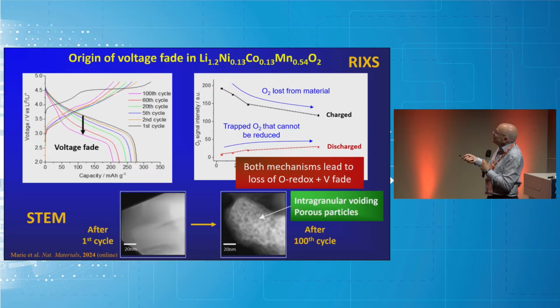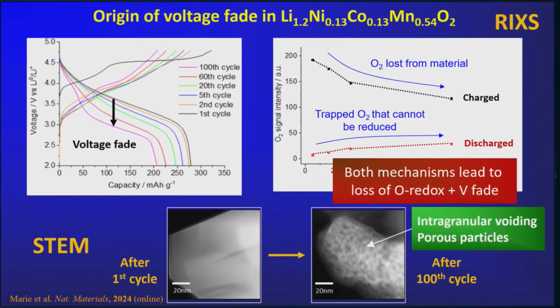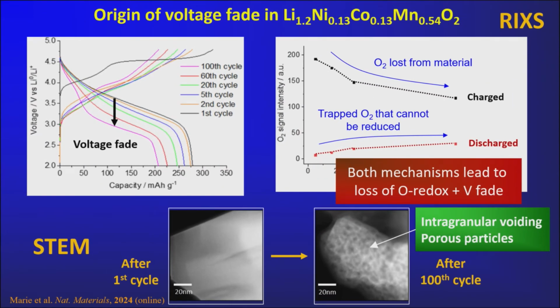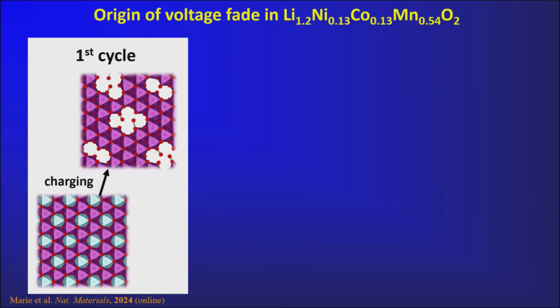And if you look in the STEM at the material after 100 cycles, you can see it's really becoming quite porous. It's getting quite large voids formed because you're breaking the material up. And what happens is that in these larger voids, where the O2 is trapped, you get more oxygen molecules in voids, and some of them can't be reduced back efficiently to oxide ions. And I'll show you that in this.